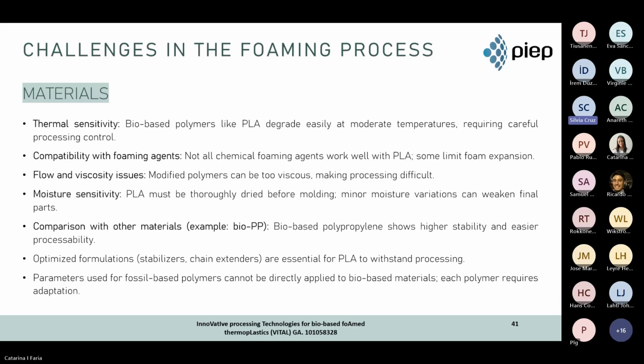Also, moisture sensitivity and hydrolysis. The bio-based polymers absorb moisture more easily. During processing, water triggers hydrolysis, reducing molecular weight. So foams will show cell coalescence, weak cell walls, and loss of mechanical strength. So drying and strict moisture control are essential.